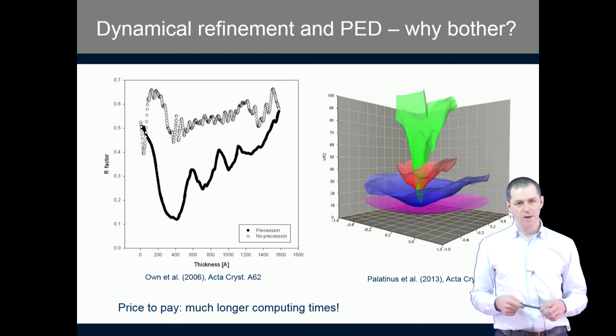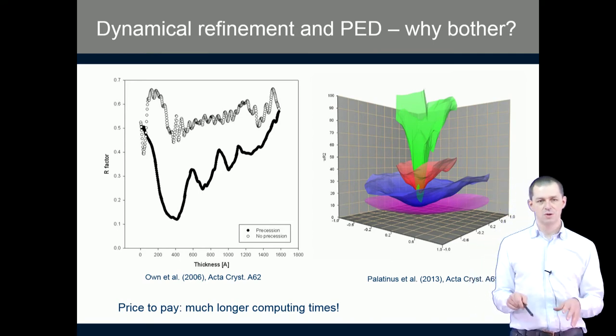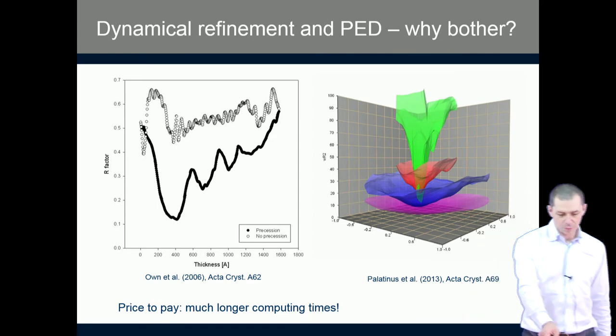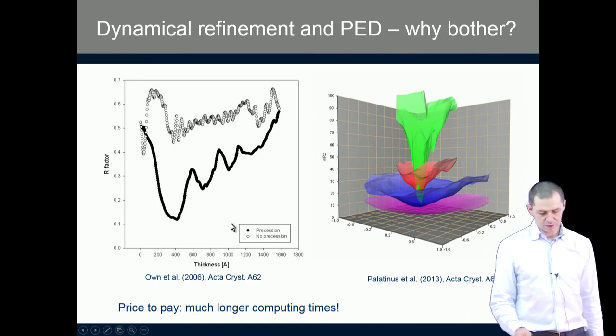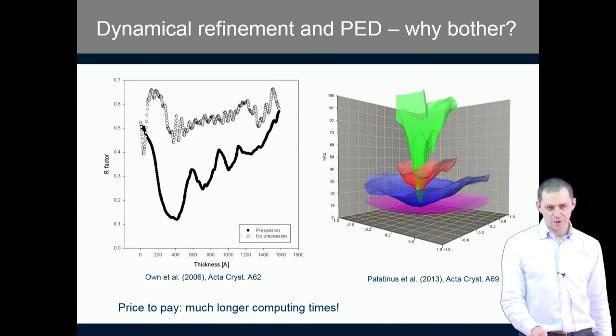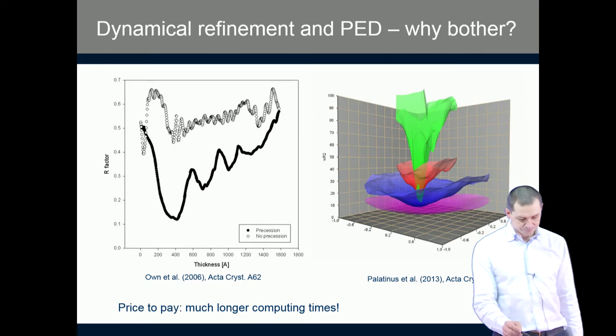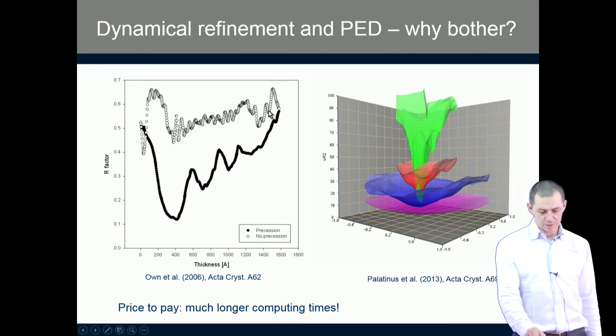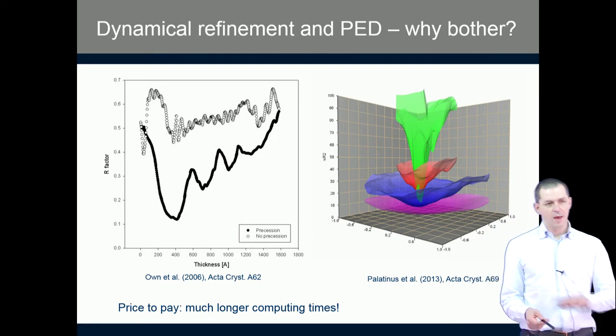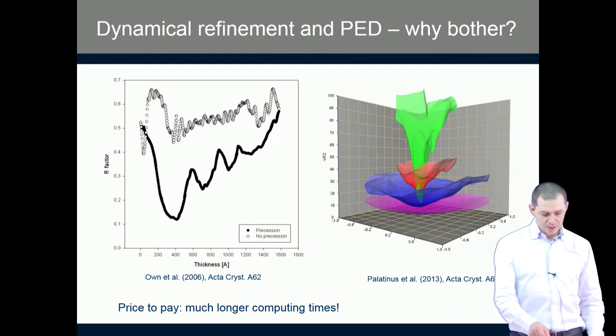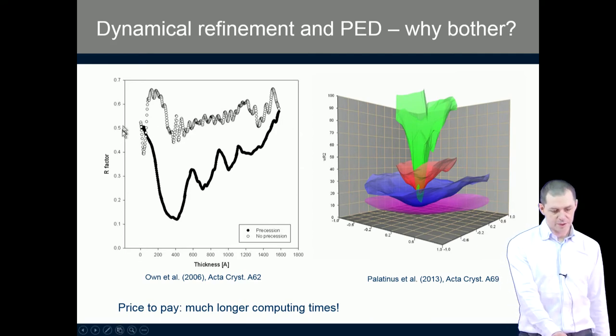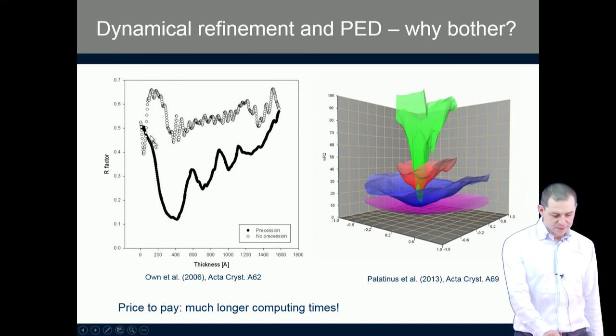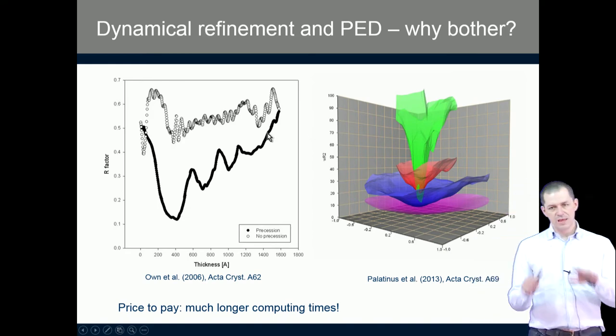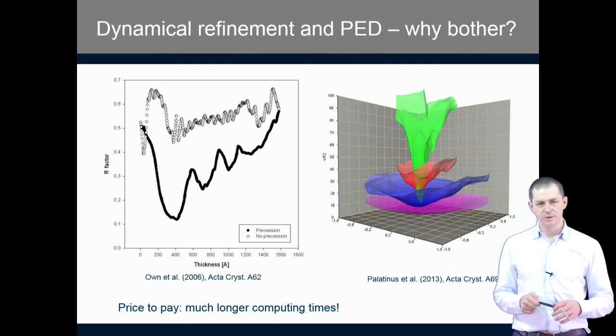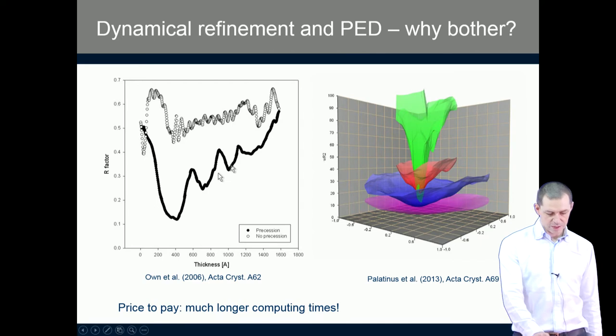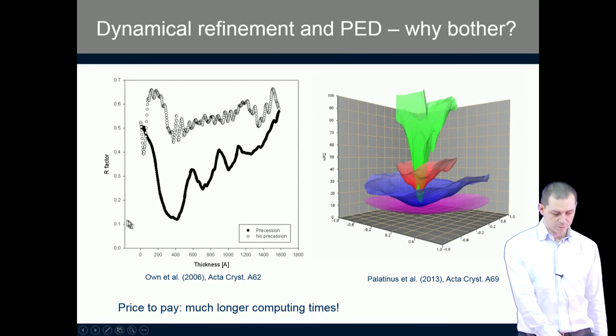And these plots do not show why it is so, but they show that it is so. The left plot here shows an R value as a function of thickness for a gallium indium tin oxide. And the empty circles are R values calculated from a diffraction pattern without precession. And you see that the R values oscillate around 50%, 0.5, with no clear minimum. And this curve here is obtained from the same diffraction pattern, but collected with precession electron diffraction. And you see that there is a nice, well-defined minimum with quite acceptable R value of about 12%.